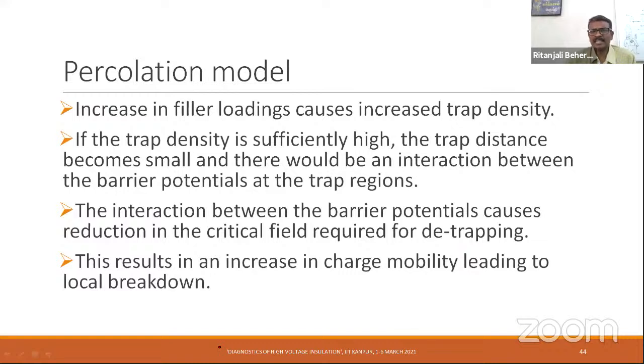What is this percolation? This increase in the filler loading causes increased trap density. Obviously, what takes place is at each filler, the charge gets trapped at the interface. So when the filler loading gets increased, the charges getting trapped are also increased. And if the trap density is sufficiently high, the trap distance becomes small. The distance between the charges that are getting trapped or surrounded by the filler becomes small, and this would increase the interaction between the barrier potential and the trap regions. This would enhance the field there, and the interaction between the barrier potential causes reduction in the critical field